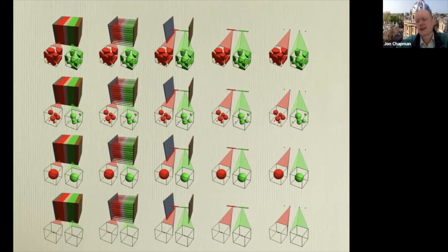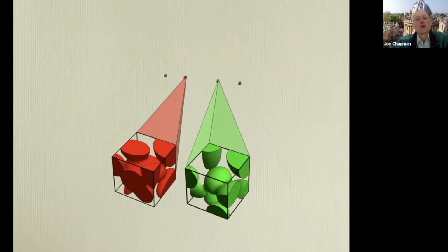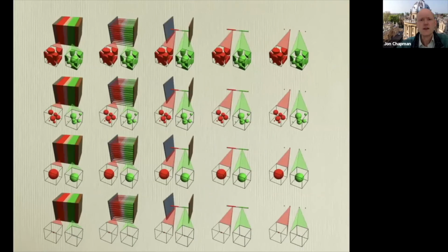That means the electrolyte sorts itself out very quickly, so you don't have to worry about solving for the electrolyte. Concentration is just uniform. Then instead of having a representative cell problem at every point in that one-dimensional thing, you just have one representative cell problem for the whole anode and one for the whole cathode. That's effectively the single particle type of model. So that's the macro scale.